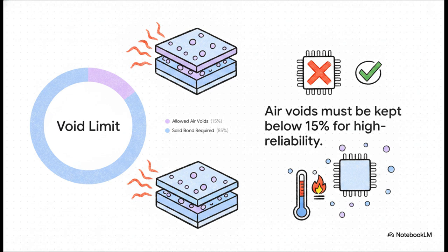That means, at a bare minimum, 85% of that incredibly thin 20 micrometer bond line must be solid, flawless, uninterrupted contact. Because if there are too many air bubbles, heat simply gets trapped and the chip will literally cook itself to death. No way around it.